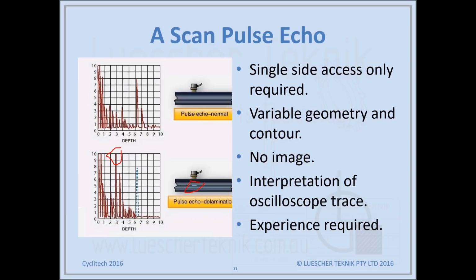The other thing we can tell is that because the amplitude of that signal is quite high, that flaw or defect is a good reflector of sound. Something like a planar void or a foreign object, which is very reflective, will give us that amplitude. So from the amplitude of the signal we can tell what type of flaw or defect that might be.